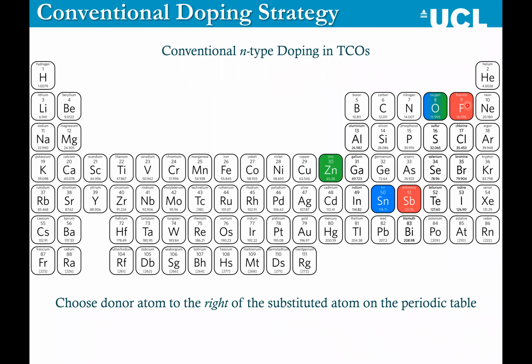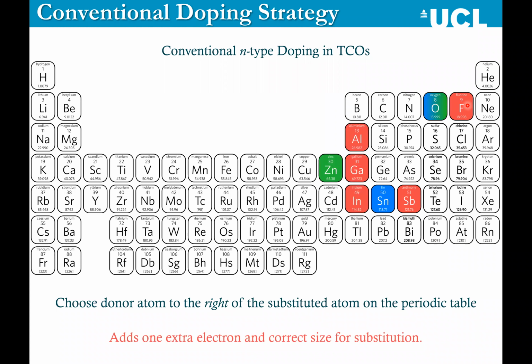Similarly, if you think of zinc and oxygen, for zinc oxide, you could go 1 to the right for zinc, and typically gallium is the best dopant, or you can go 1 to the right to fluorine again. But it appears that people for generations have used this kind of conventional doping strategy, and it has worked. And it worked for tin-doped indium oxide, it's worked for gallium-doped zinc oxide, and these systems are used in devices.